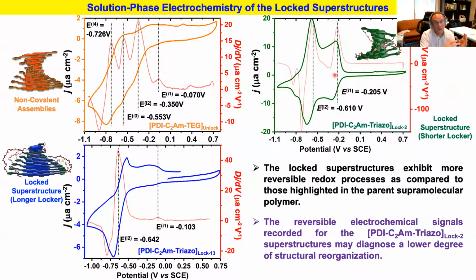That tells us that, of course, you have an electron transfer to the electrode that is faster, since they are being monitored at the same scan rate, but also you probably have a lower degree of structural reorganization accompanying the n-doping of this material. That's another interesting aspect of the work we are doing here: we are hypothesizing that we can limit to some extent structural reorganization upon n-doping. And we are currently working more towards this direction.